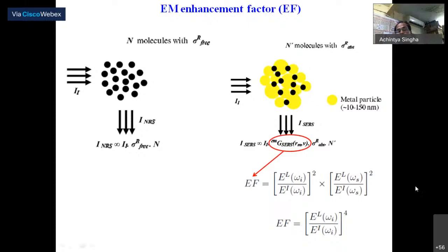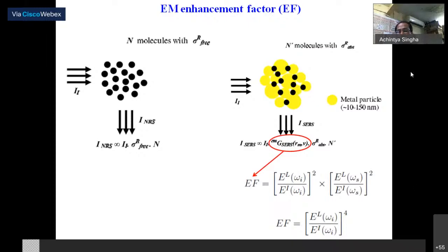The magnitude of this enhancement factor is of the order of power 4. If E_I is the field before the nanoparticle, and E_L is the localized field after the nanoparticle, then the total enhancement will be of the order of (E_L/E_I) to the power 4. So if your molecule is adsorbed on the surface of a metal, mostly the SERS enhancement occurs with gold and silver. Those metals are very efficient because this localized electric field depends on the dielectric properties of the material.